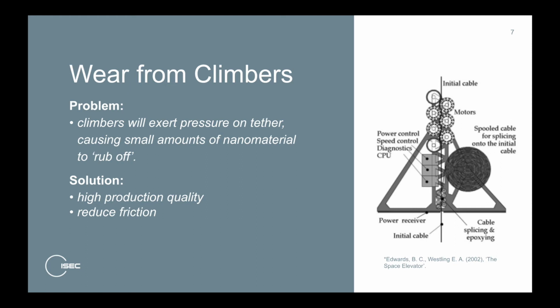When spinning nanomaterial fibres, it's important to make sure that there is enough surface area contact so that the entire structure is strong, not just the individual fibres. To avoid wear, we may also need to reduce the amount of friction between the tether and the climber, possibly through the use of magnets. Any damage created, however, we would assume to be small, and therefore could repair it regularly using maintenance climbers.